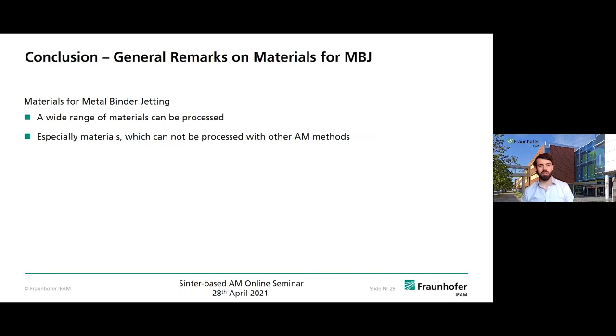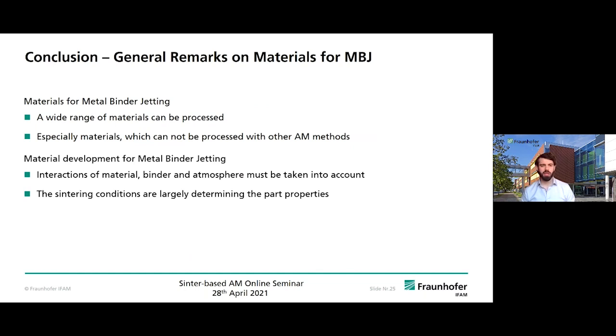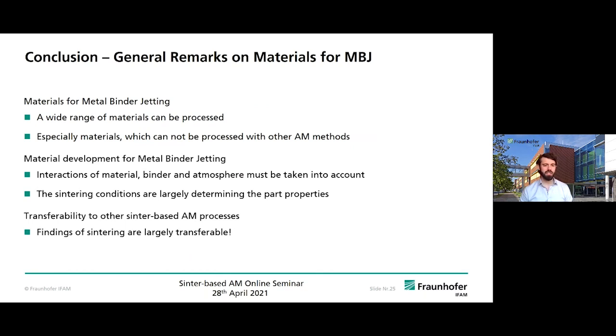And now I will come to my conclusions. As already mentioned in the beginning, metal binder jetting can process a wide range of materials, especially materials that cannot be processed with other AM methods, and that's one of its benefits. When developing materials for metal binder jetting, interactions of the material, binder and the atmosphere have to be taken into account, especially the sintering conditions are largely determined by the material, and they are determining the part properties afterwards. And the transferability of the findings to other processes is possible.